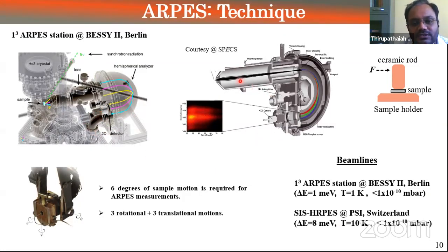And this is the cross section of one of the important components of an ARPES machine. I think many of you know it already. Here you have electrostatic and magnetic lenses, which control the path and kinetic energy of the photoelectrons. Here they get analyzed, and then finally they fall onto this detector and are collected by the phosphor screen. And this is what your raw data looks like, where along the y-axis we have the kinetic energy of the photoelectron, and along the x-axis we have the takeoff angle.